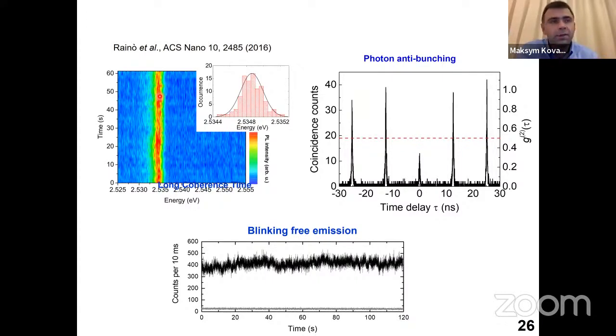So it's a stable single photon emission. There is clear single photon emission confirmed by the anti-bunching experiment, and these quantum dots do not blink much. Just to put it in perspective, before the perovskite quantum dots, all the other kinds of colloidal quantum dots have been unstable, they blinked a lot, and at such large sizes, they had not been single photon emitters.